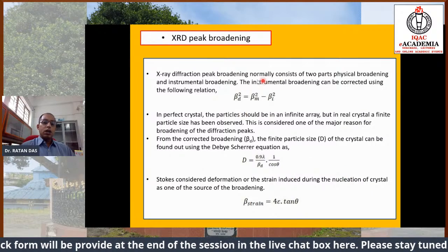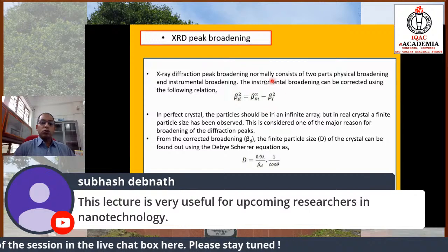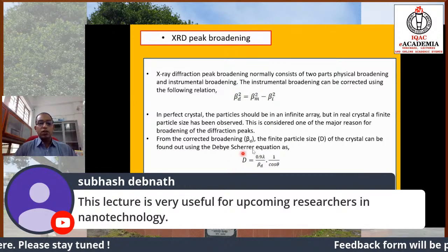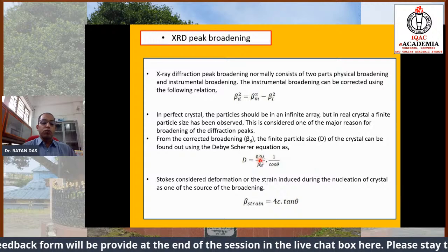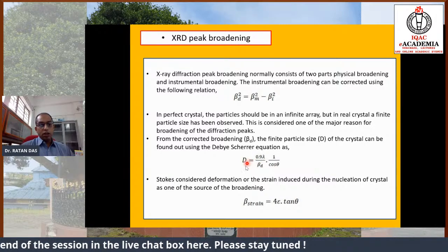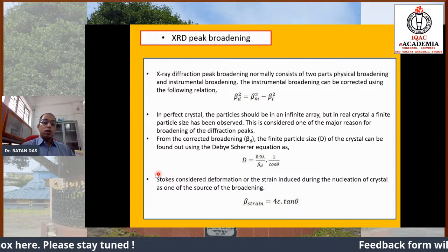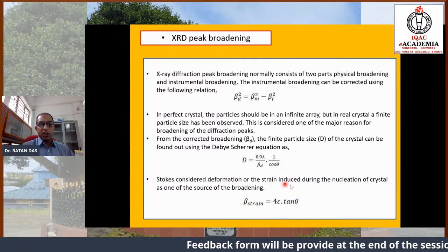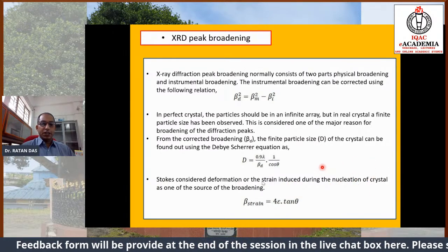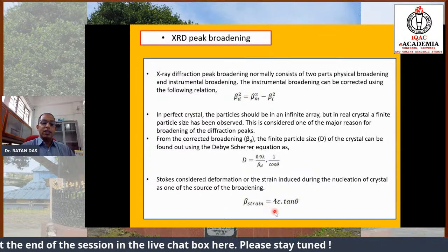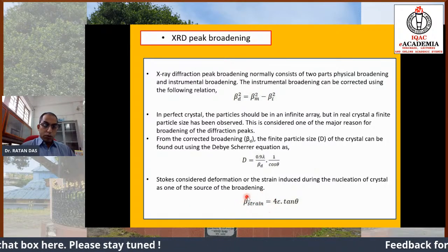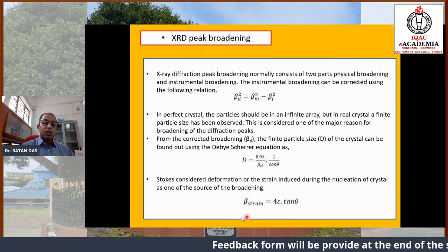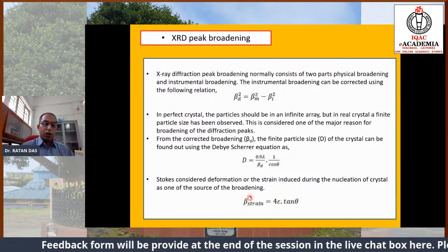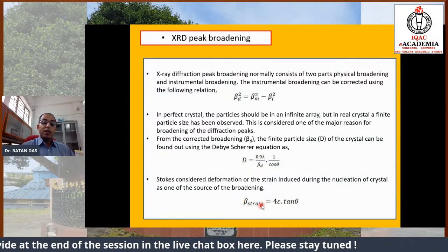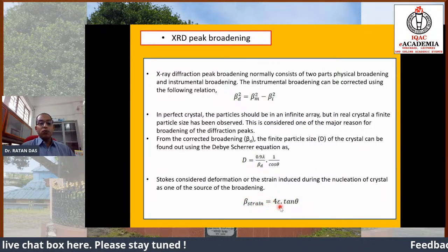As I have told earlier, we may get rid of the instrumental broadening through this formula. We may obtain the size through this Scherrer formula, D is equal to 0.9 lambda by beta cos theta, because here we have put 0.9 as the value for K, and that is for spherical nanoparticles. Stokes in 1953 considered deformation or strain induced during the preparation of the crystal structure. So Stokes gave the idea of how the strain value affects the width beta, the full width at half maxima. The significant amount the strain is giving is 4 epsilon tan theta.